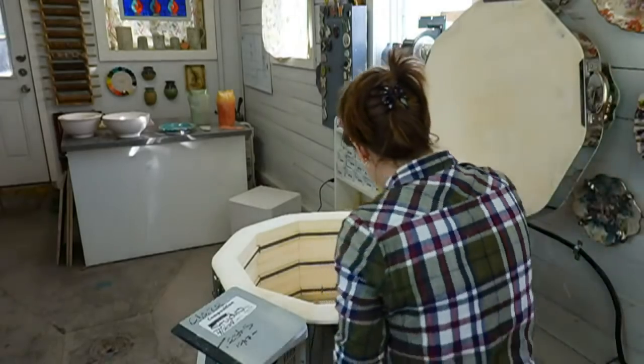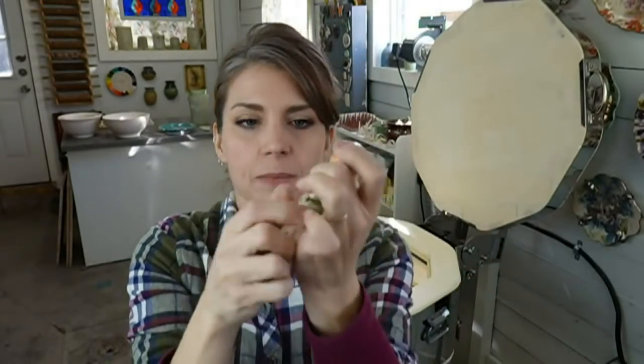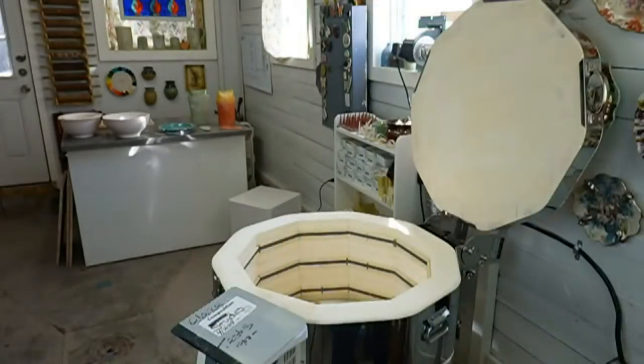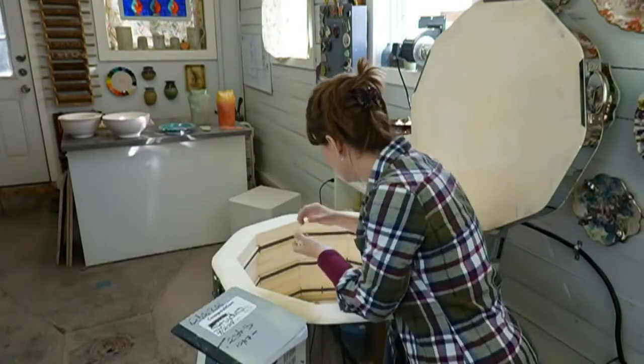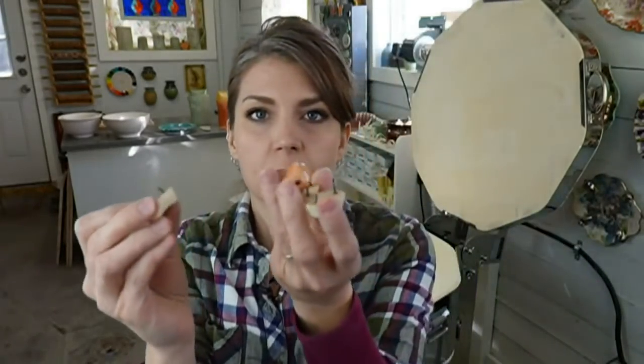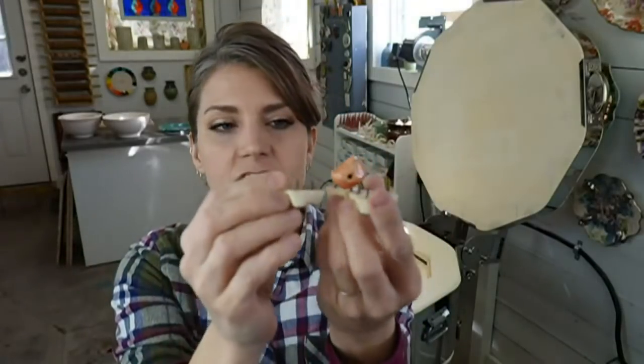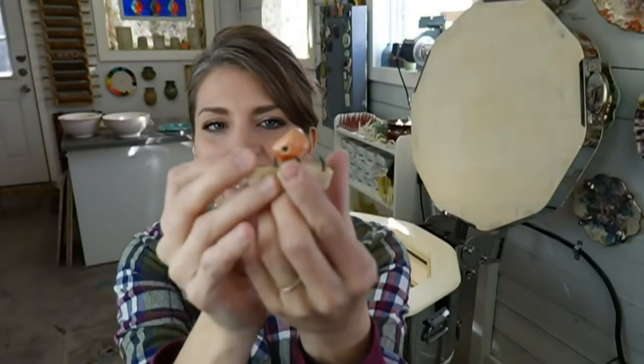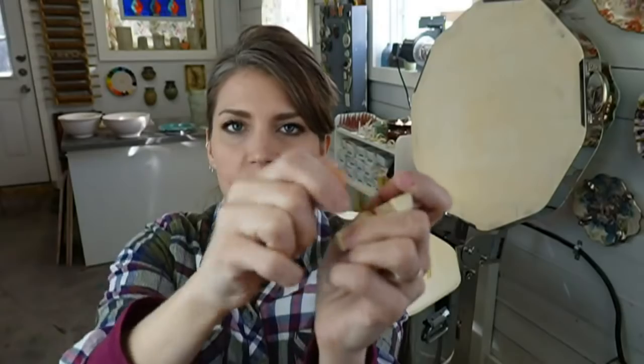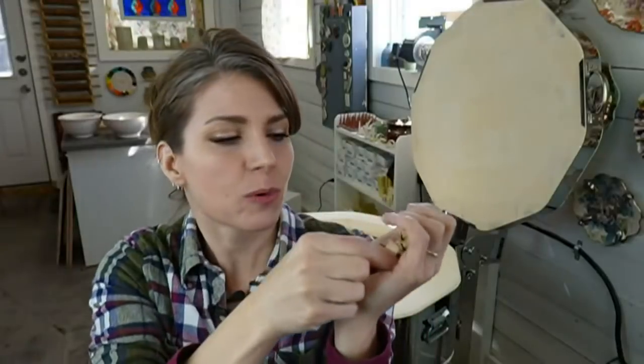And then I've got a bunch of beads. Same thing with your beads. I glaze them all the way around, so I fire them on the little stilts. So you just pull them off like that. And then I'll go back and sand them later. Now sometimes I will have a teeny weeny bead, like I did here. So this bead was too small to go on one of these. So what I did is I took 3 of them, put them really close to each other, and I set it on the 3 little prongs that it made. So that's the way you deal with teeny weeny things. You build your own kind of support structure using 3 of these instead of 1.